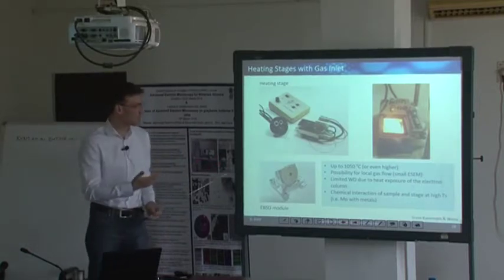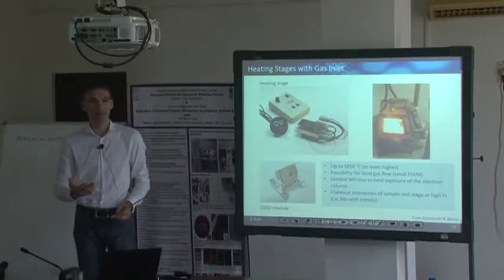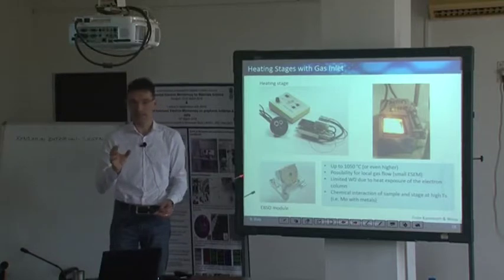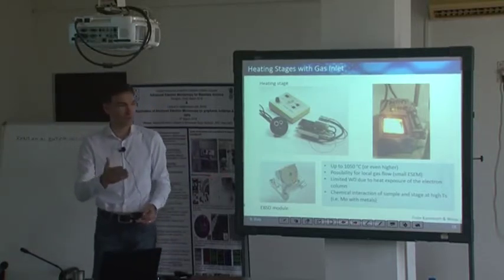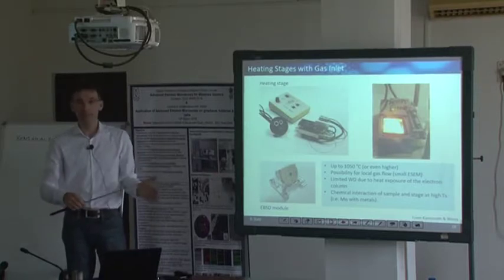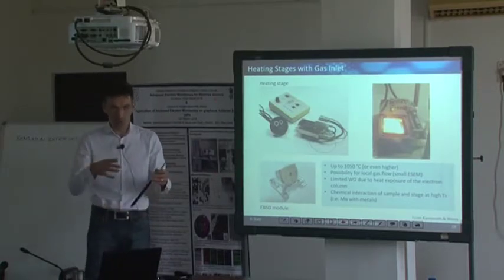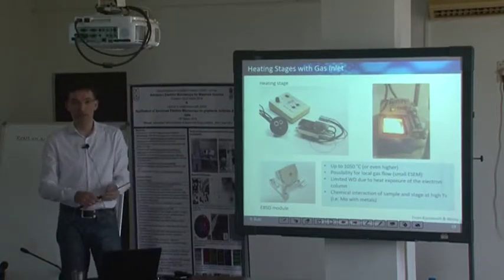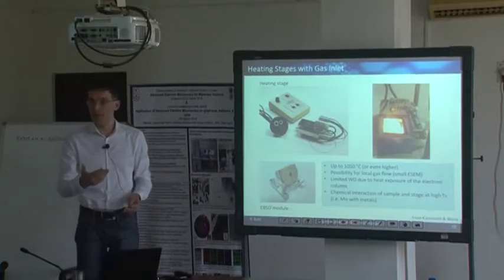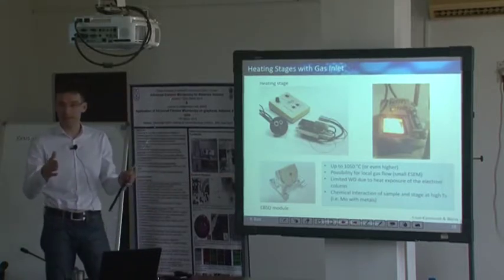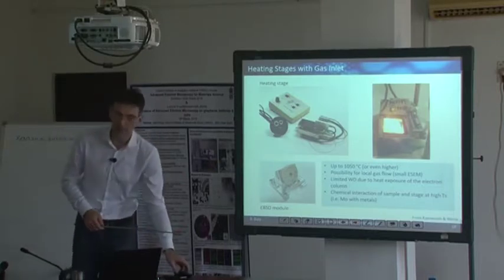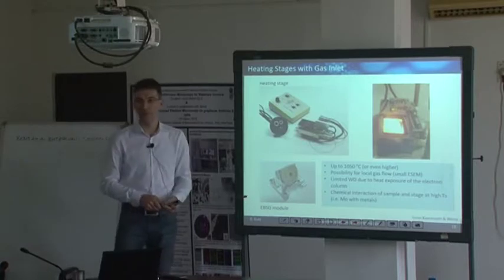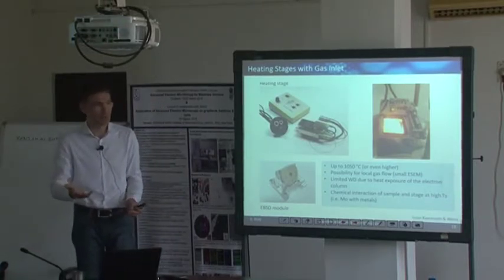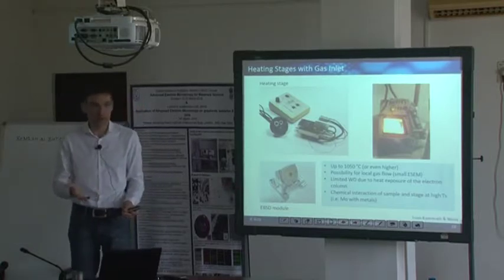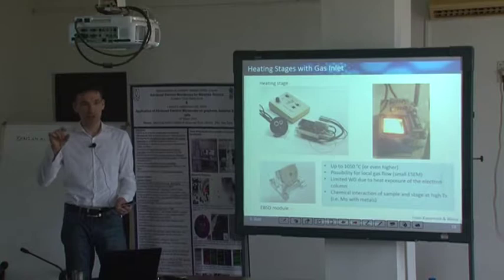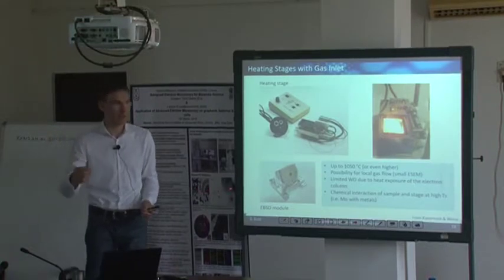So in principle, for such experiments, and this is very challenging, you would need ways to measure the temperature on a very localized scale, for example by electron diffraction, because heat causes thermal expansion, which causes a shift of your lattice planes or a change of your lattice parameter. By that you are able to observe changes of your diffraction pattern and the spacings in it. But you have to be very accurate to achieve that. The thermal expansion coefficients of common crystalline materials are of the order of 10 to the minus 6 to 10 to the minus 5, and observing any temperature change of a few Kelvin necessitates such an accuracy in electron diffraction.